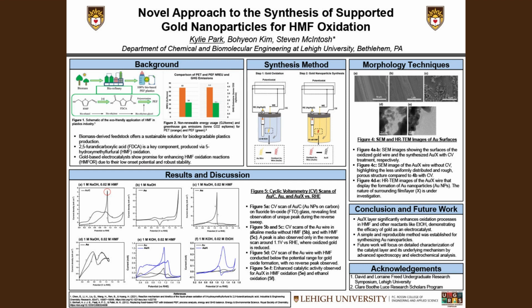In conclusion, a simple and easy synthesis method was established and showed promising results of enhanced HMF oxidation activity, which was also showcased in similar processes like ethanol oxidation. Our next step is to further investigate what the gold nanoparticles are supported on, X, and the underlying mechanism of the synergy between the AuX catalyst and HMF oxidation activity by conducting more spectroscopy experiments and electrochemical analysis.